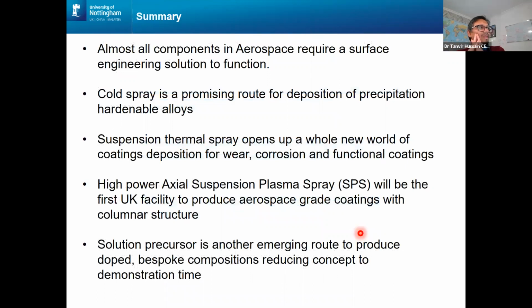So as you can see, all aerospace components require surface coatings to function. Cold spray is a really nice way of depositing metallic coating without melting. Suspension thermal spray is an emerging technique which can produce columnar type structure, which is really beneficial from a thermal cycling point of view. Solution precursor is another new technique where you're using salt as opposed to particles in a suspension to develop different coatings. Essentially, there's a lot to explore.